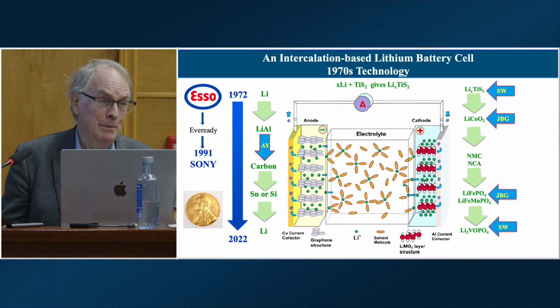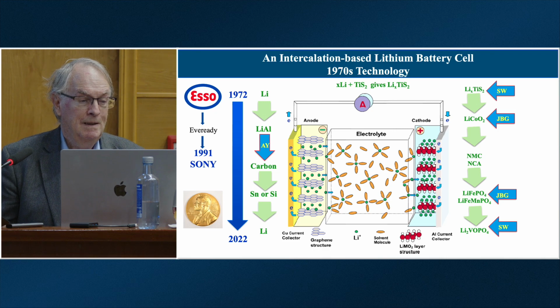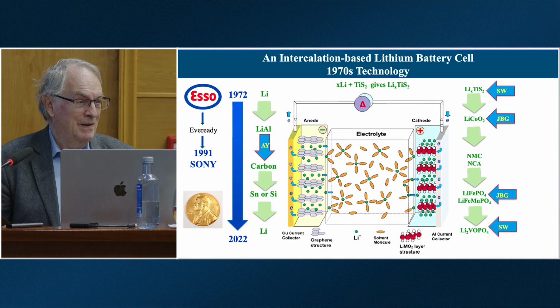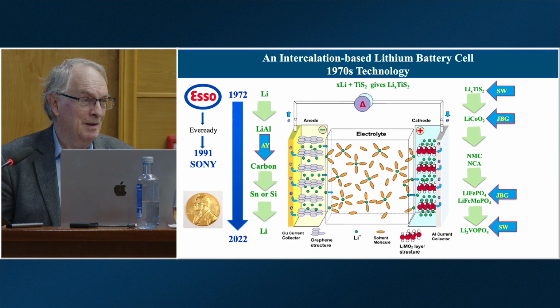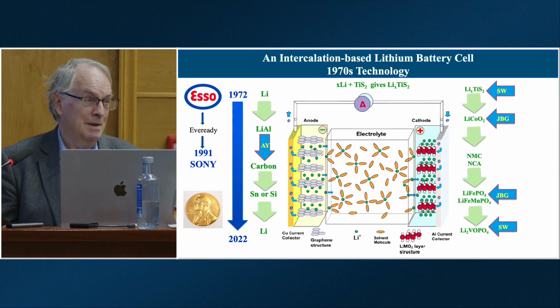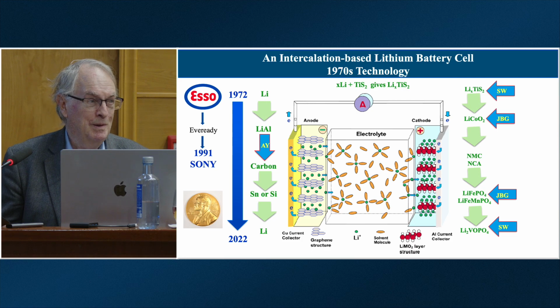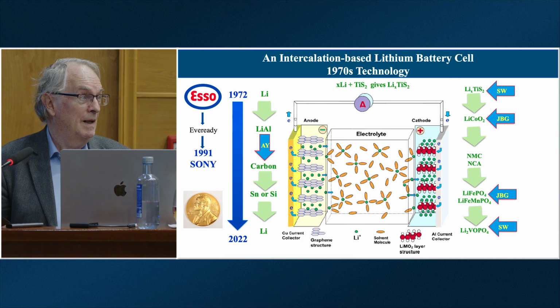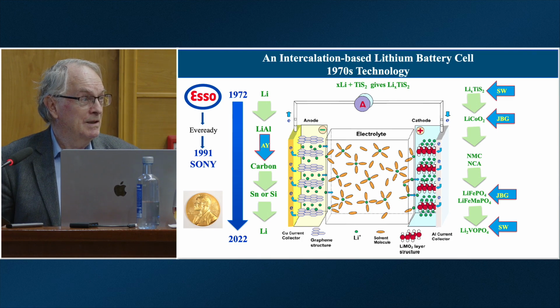So we start out with titanium disulfide, and I won't go into the history of that, but we were interested in superconductors, and tantalum disulfide was a superconductor. If you put electron donors into it like lithium, potassium, you could change its superconducting properties. But obviously we're not going to use tantalum in the battery, so we switched to titanium disulfide. It's the lightest, but has another huge positive trait.